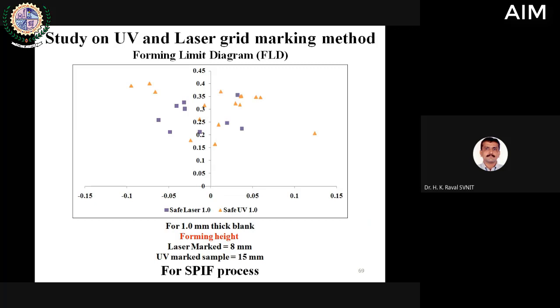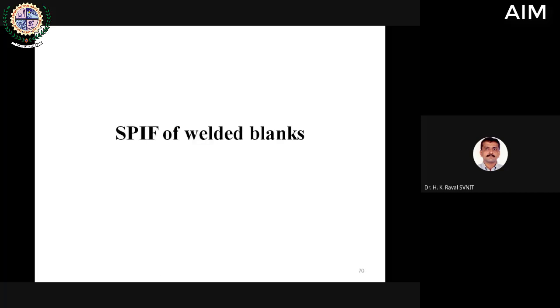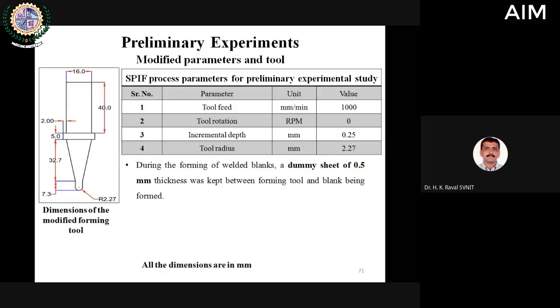This is the forming limit diagram plotted for the UV and laser mark, and it is observed that the UV mark component has got higher forming compared to the laser mark component. Laser marked components have more chance of failure, early failure I would say. UV mark components can be formed a little deeper, and that was already presented earlier in a couple of slides before. Then welded blank single point incremental forming was done.